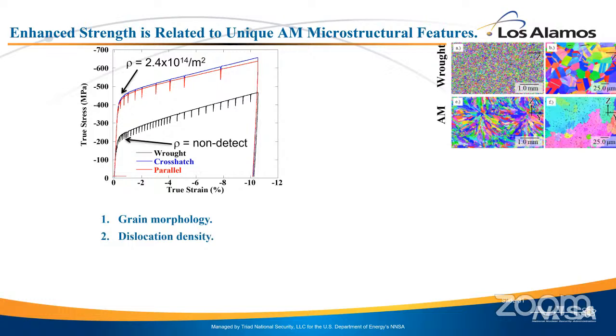The dislocation density affects the strength. If you look at the dislocation density at the start, when the material is either in the as AM or as wrought state, we can't even detect it with diffraction. We see dislocation density through peak width. In the wrought material, the peaks are at our instrumental resolution, so we can't even detect dislocations. That means they're probably at about the 10 to the 12, 10 to the 13 per meter squared level. In the AM material, they're an order of magnitude higher, at least. They're 2 times 10 to the 14th in the as AM material. So that also obviously affects the strength of the material.